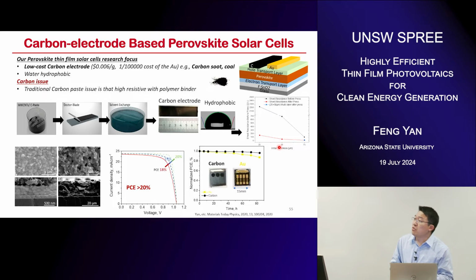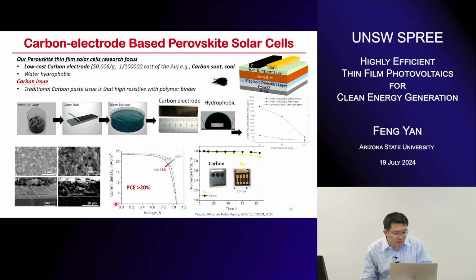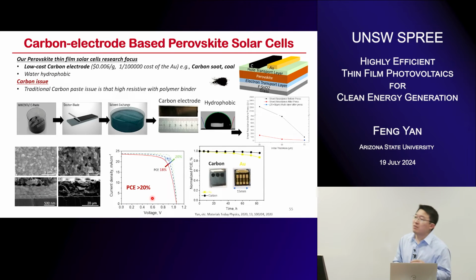One way is to reduce the cost of manufacturing, because we know that the carbon is dirt cheap, right? So it's just thousands or 10,000 times less cost compared to the gold or other metal. And here we started with a very simple device architecture, but recently we can demonstrate around 20% using the carbon. So it's a pretty cheap approach. And compared to the gold, the carbon demonstrates desired stability because the carbon electrode can repel the moisture based on its hydrophobic behavior.